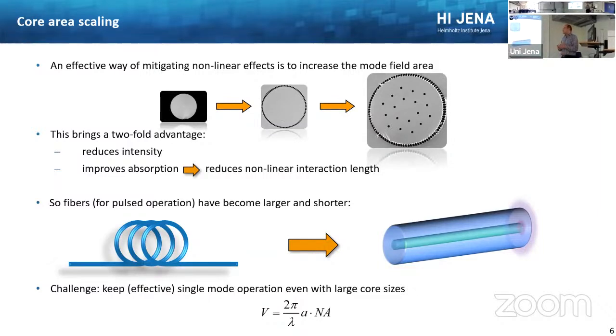Now the challenge is that just increasing your waveguide is normally not going to help you with your diameter, because if you just make your waveguide larger, the so-called V parameter that you see at the bottom also grows. This is V, which is dependent on a, the diameter of your fiber core. And when this parameter grows, it means you add additional modes to your fiber. This reduces your output beam quality, which is normally not what you want to have.